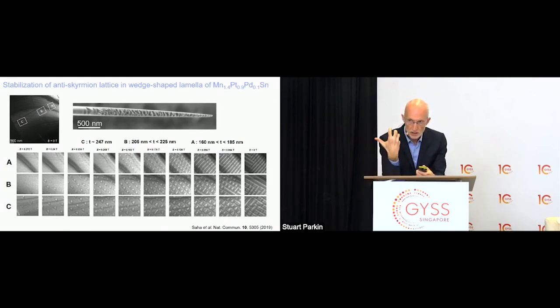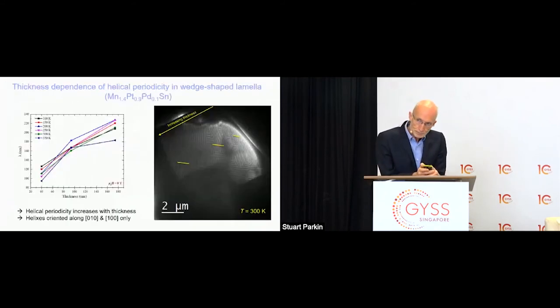So in this case, the array of anti-skyrmions has disappeared, and instead the system energy is stabilized by forming helical structures. And it turns out in these anti-skyrmion systems, the helical structure is directed along one of two perpendicular in-plane directions. And it turns out this helical structure has very interesting properties. Maybe you can see here in this Lorentz micrograph on the right-hand side, a series of white and black lines. These correspond to the in-plane component of the magnetization changing from a right to a left direction.